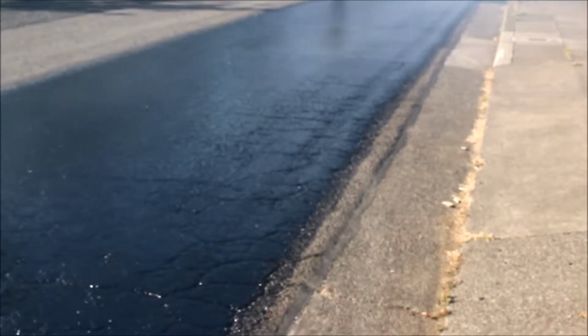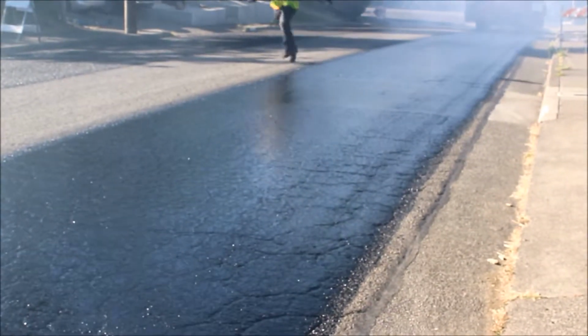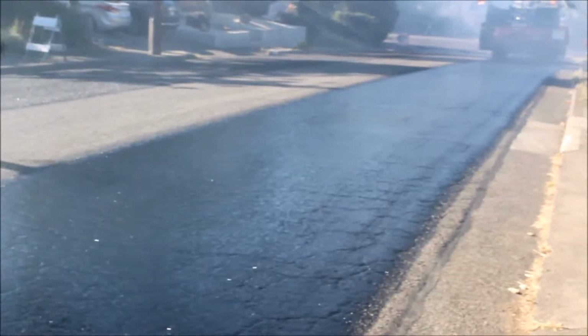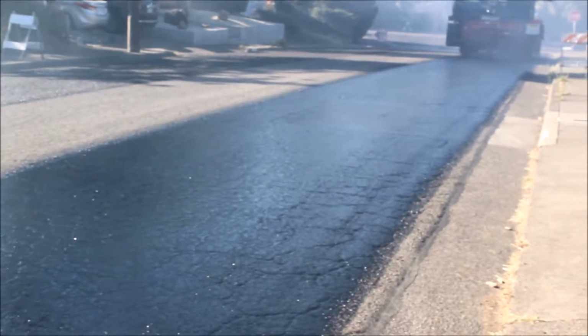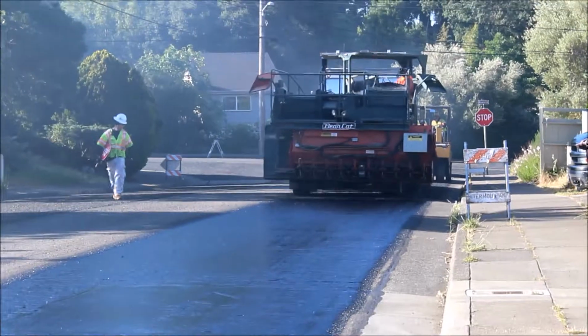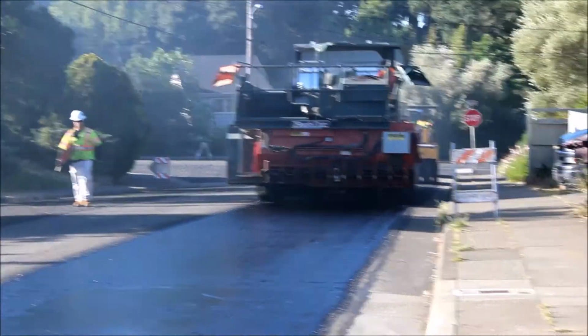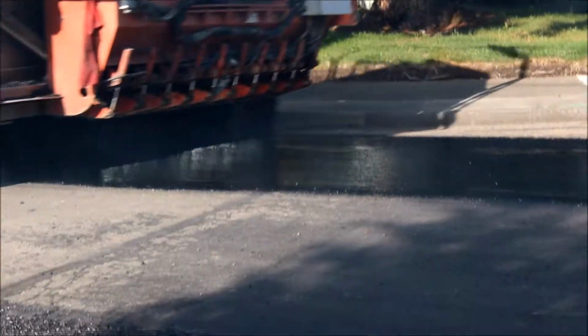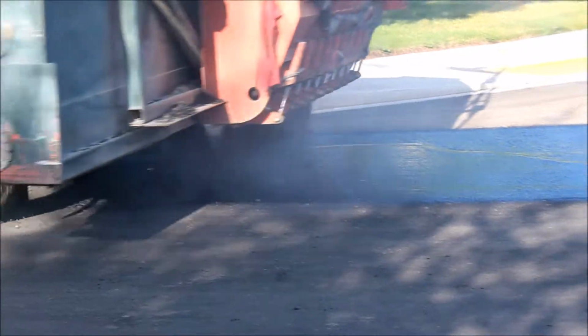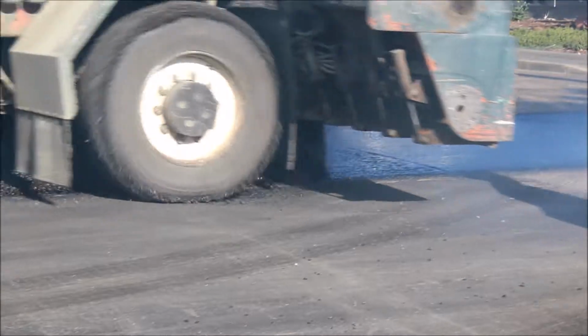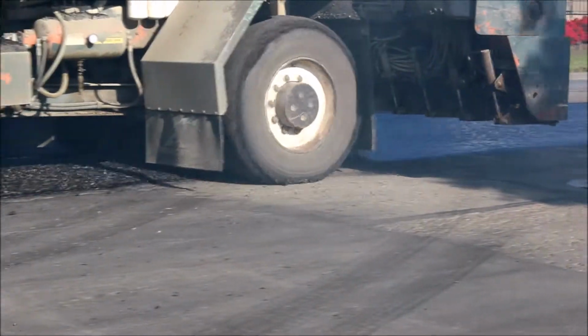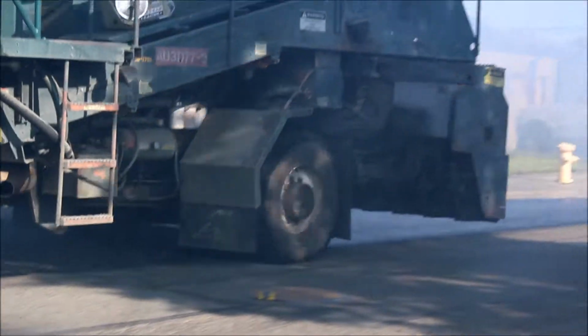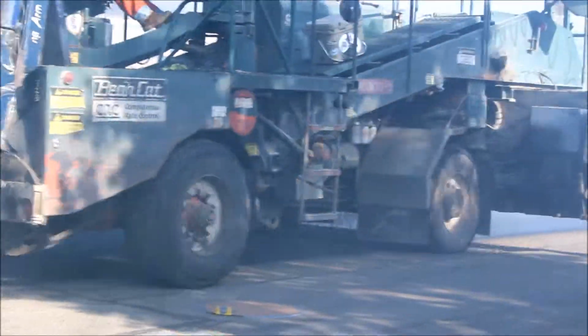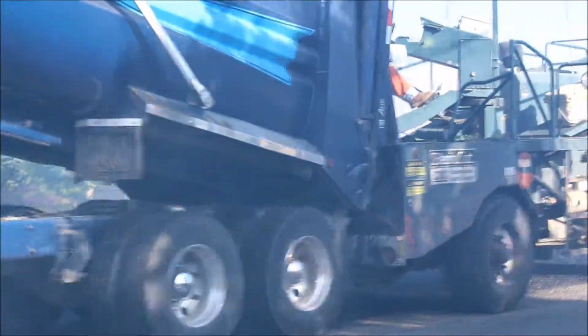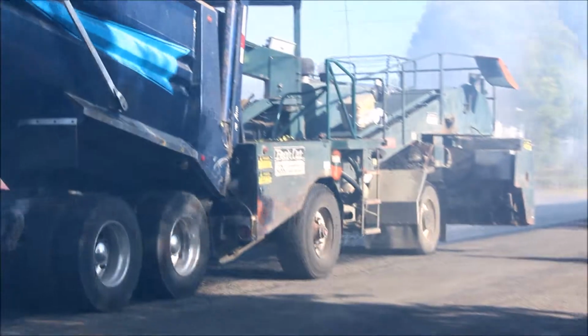The chip goes down onto the emulsion binder while it's still hot. This should be coming out of the machine at about 375 degrees. I'm sure you guys can feel how hot it was. The chip is put down while the binder is still at least 325 degrees. Because that chip is hot and because it has the asphalt around it, it's going to help bind to the asphaltic emulsion.